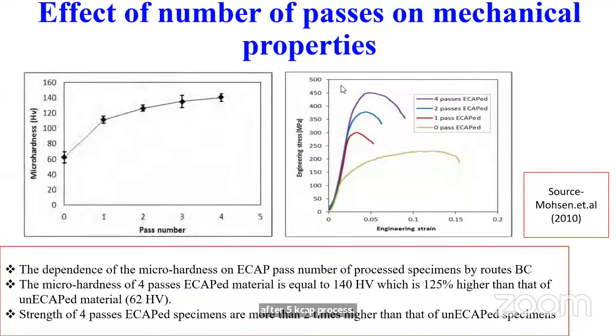This is the effect of the number of passes on mechanical properties. You can see as the number of passes increases, the hardness value increases. Similarly, the tensile strength increases for the 4 pass ECAP sample when compared to the parent metal. This is the parent metal, and its ductility is more. The ductility is reduced for the materials processed by 1 pass, 2 pass, 3 pass, but the strength is improved. After 4 passes, it is in the range of 450 megapascal.